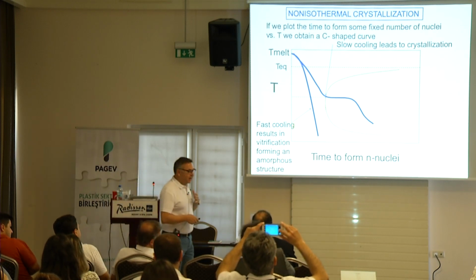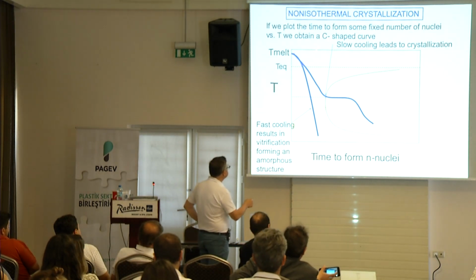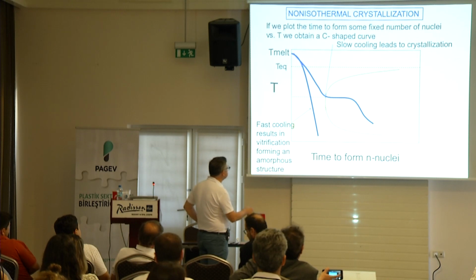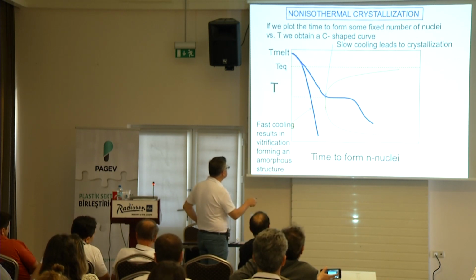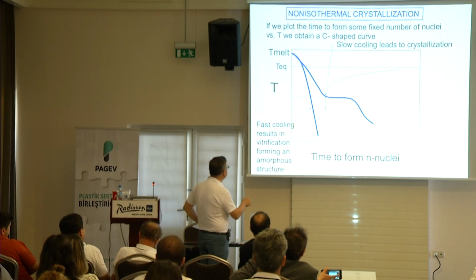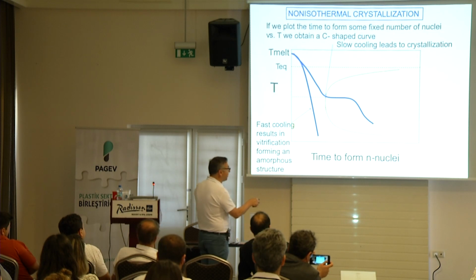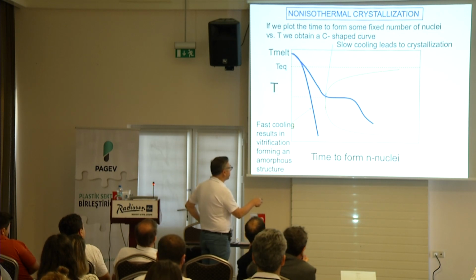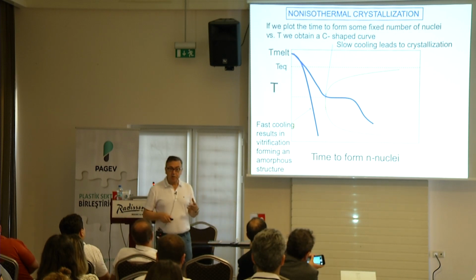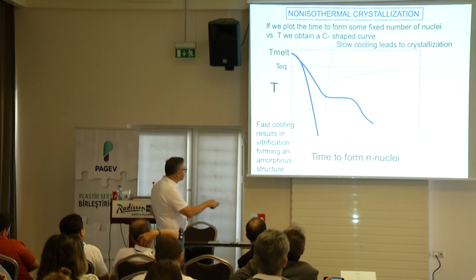All right, so here's a typical, what we call the C-shaped continuous cooling diagrams. This curve is the equilibrium melting temperature, remember we talked about? And Tg is somewhere below here. And this is the curve. This curve basically says, if I am at this temperature, it takes this long to create a fixed number of nuclei in the material. So when you're closer to the equilibrium melting temperature, it takes much longer because the driving force is less, the critical size for nuclei to form is larger, and then you get fewer of them. And as a result, it gets longer. As you go to lower temperatures, it increases. When you approach the glass transition temperature, the opposite takes place because your viscosity dominates below here. So it goes down. So this is C-shaped.